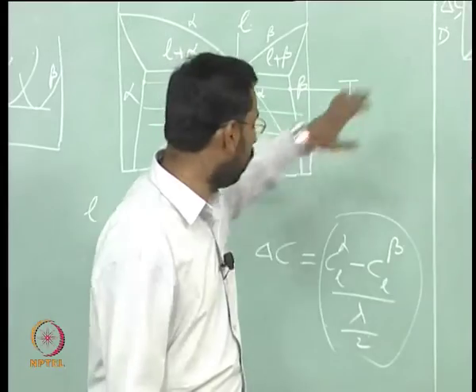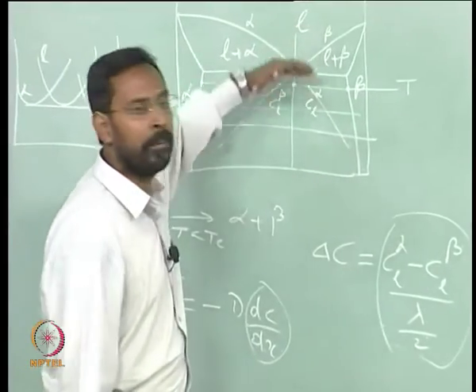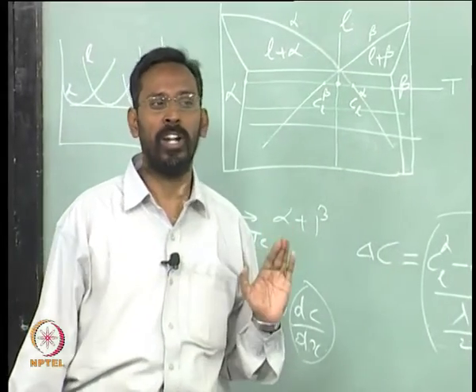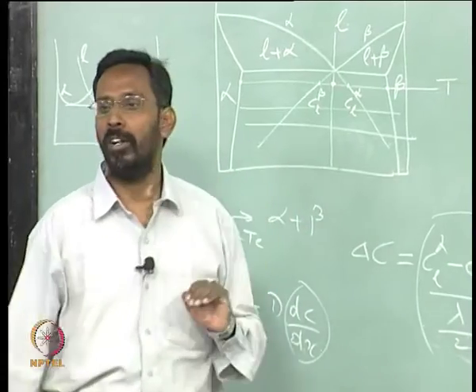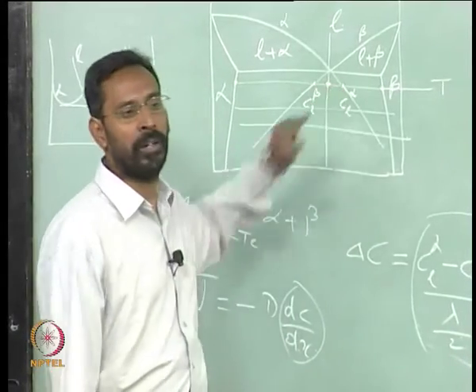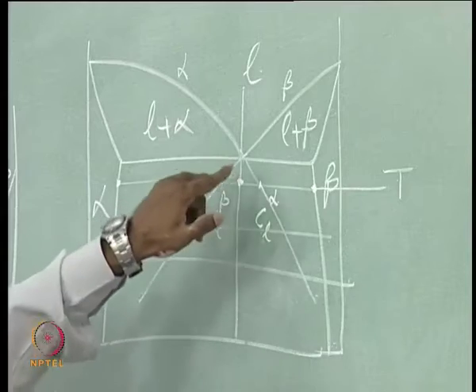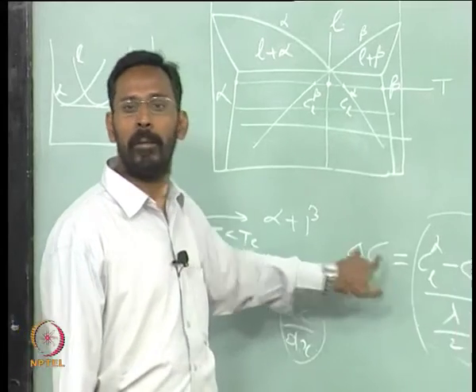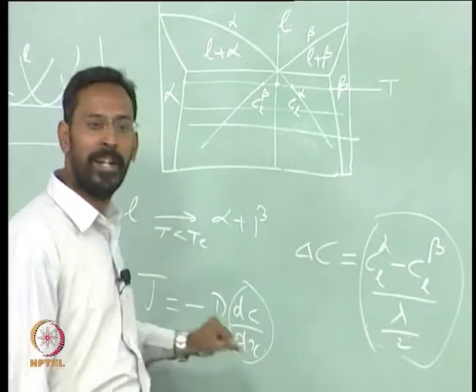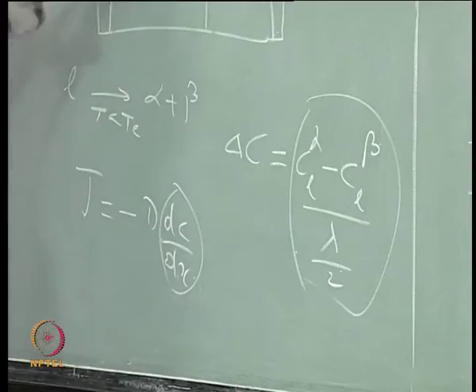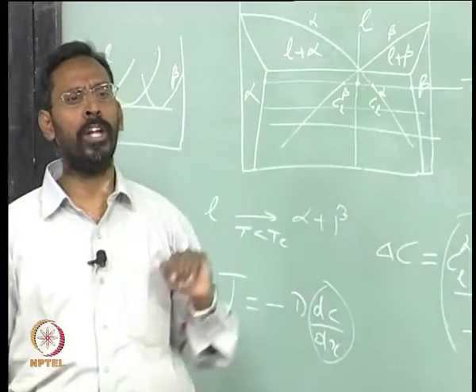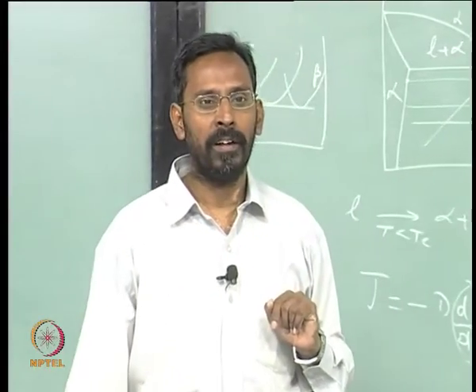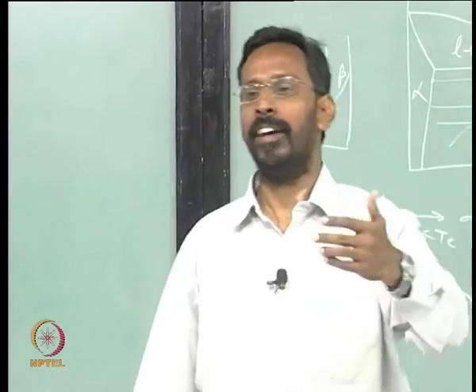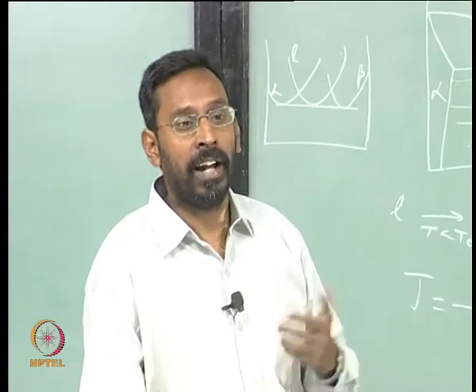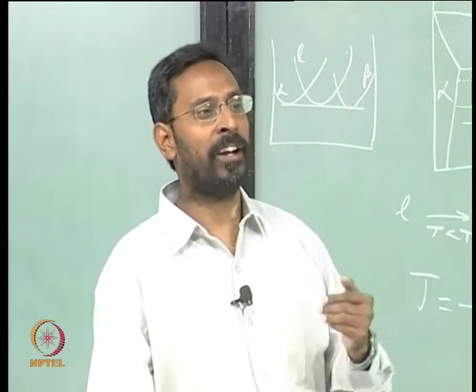You can see that until a certain temperature, growth rate is always proportional to undercooling, because the undercooling decides the delta C, and delta C decides dC by dx. As a result, at temperatures closer to the eutectic temperature, the growth rate is always decided by the delta T undercooling. So the higher the undercooling, the better.